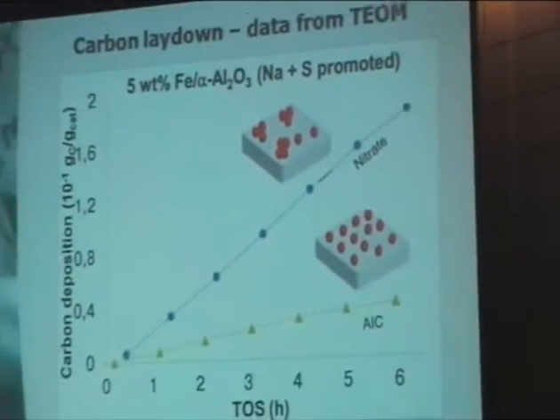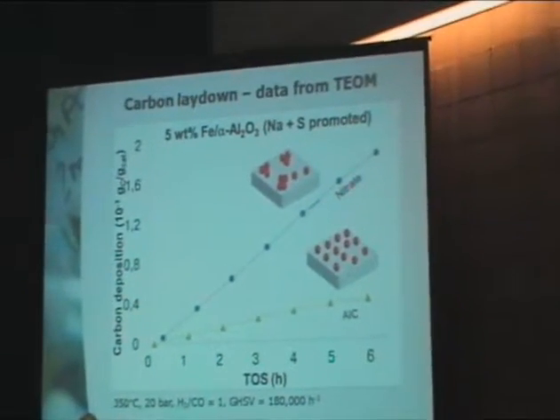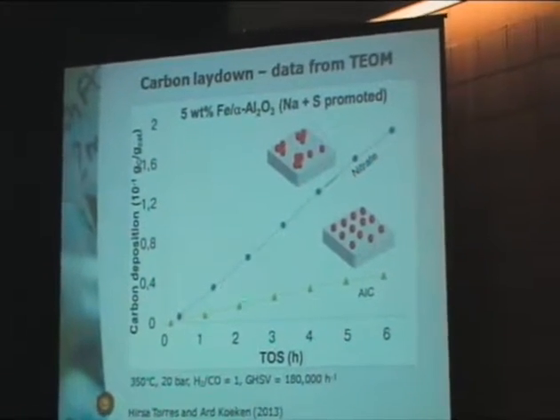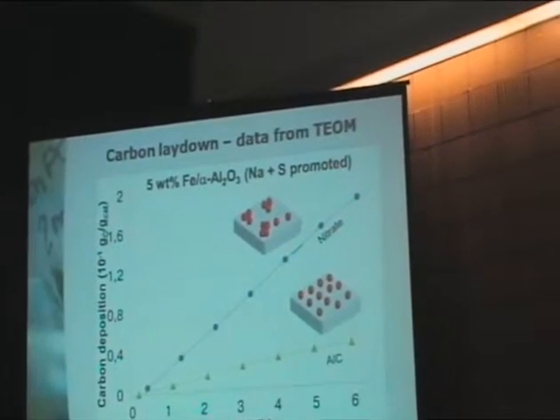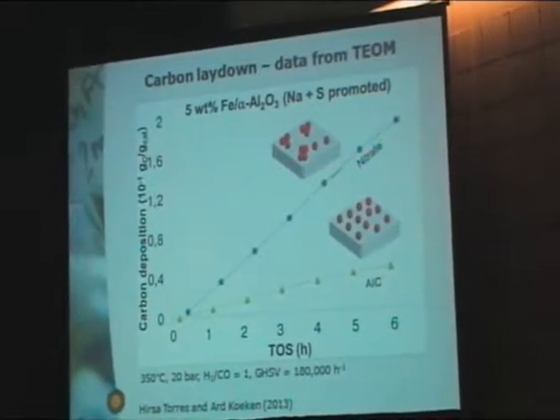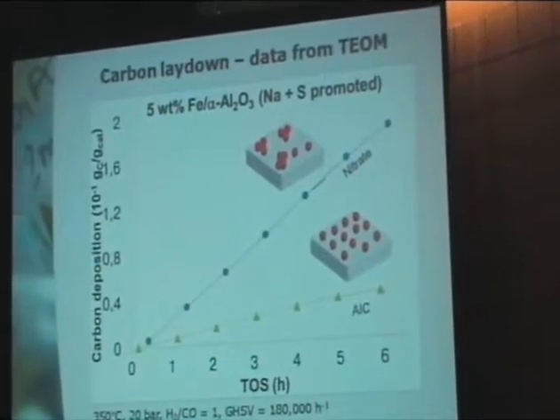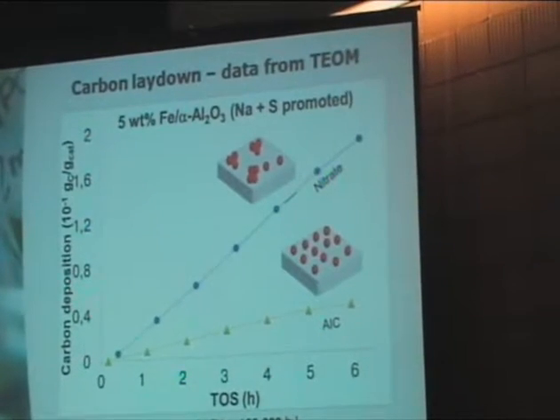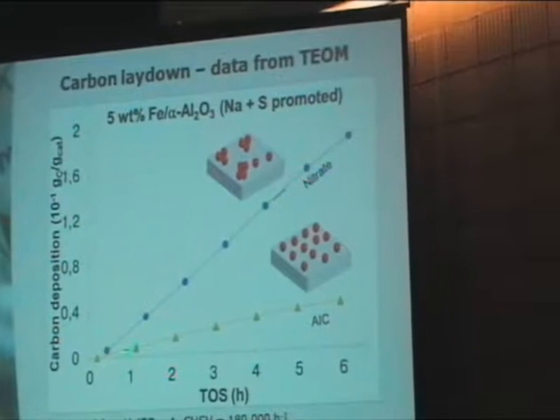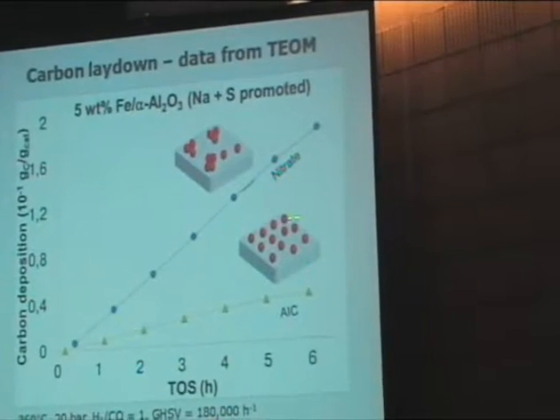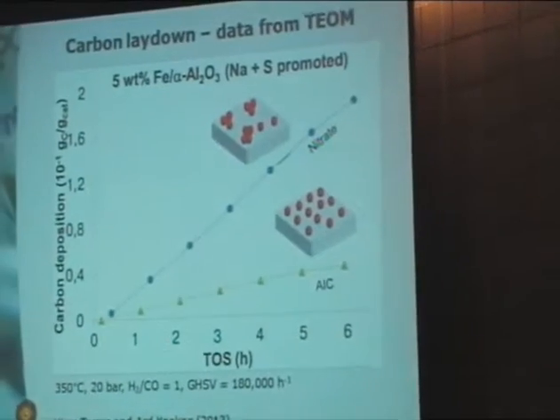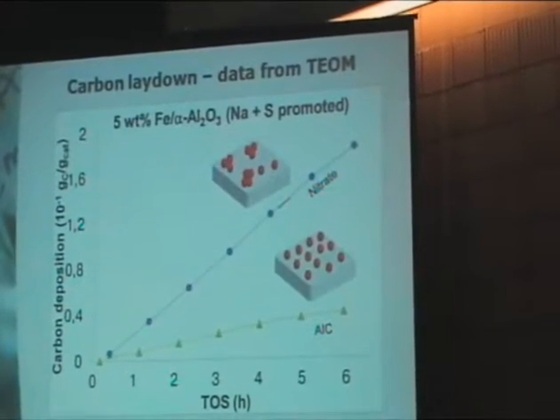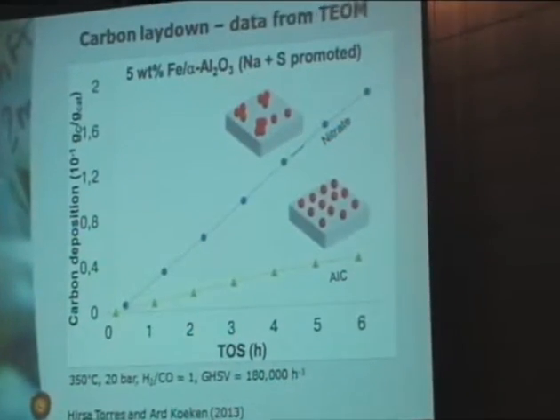But still, in this short period of time, with iron nitrate catalysts, so same loading, same iron oxide nanoparticle precursor size of about 20-25 nanometers, we see a much faster uptake of coke. This is the amount of carbon, already something like 15 to 20 weight% of carbon after 6 hours on stream, while the ammonium iron citrate, with this distribution of nanoparticles, gives us substantially less carbon deposited after these 6 hours on stream. So this is the best catalyst we have now.